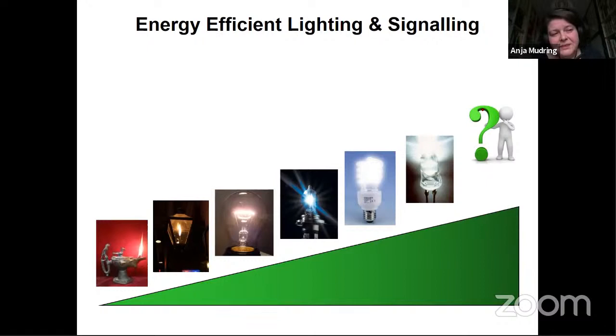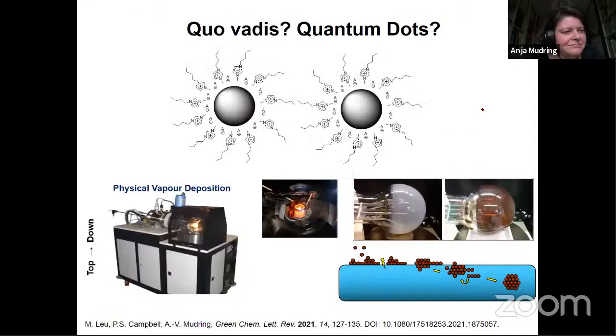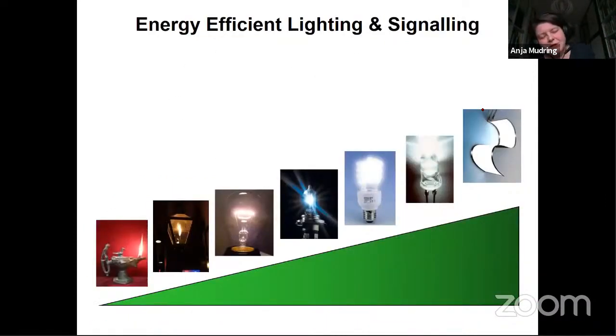But again, LEDs, is it where we really stand? No. Another idea would be quantum dots, so really go beyond what we have now. We can do that again with ionic liquids. The charm is we can use a top-down synthetic technique. Since many of them don't have vapor pressure, you can vaporize material in them. And again, depending on the ionic liquid, you can determine the size. That's really nice, but that might really not be the future, particularly thinking of that cadmium sulfide and selenide are really nice quantum dots, and they are not green materials.